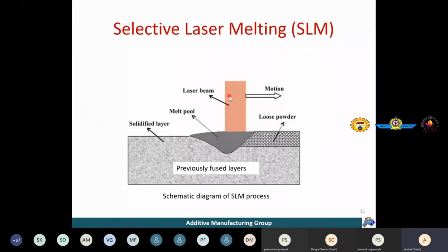If we see the selective laser melting process, you can see the schematic of this process. We have a previously fused layer or build plate. Then we have a current powder layer, and the laser beam is traversing along from left to right. On the left side we have the solidified layer. Below the laser beam we have the melt pool, and on the right side we have loose powder.